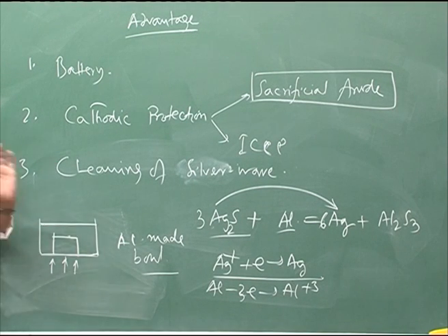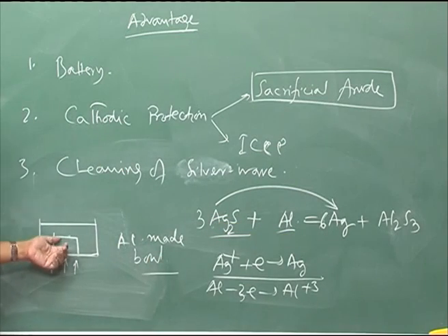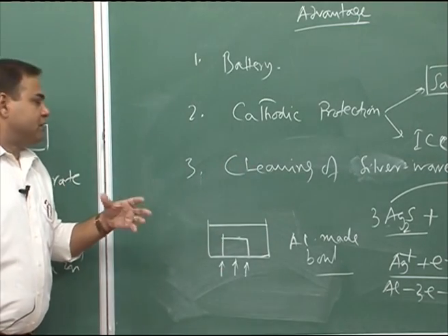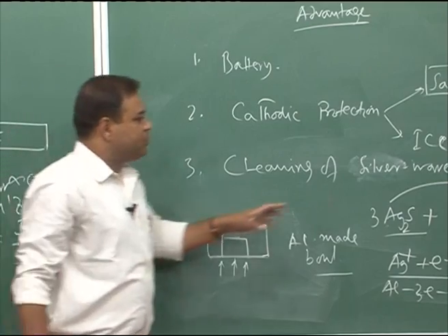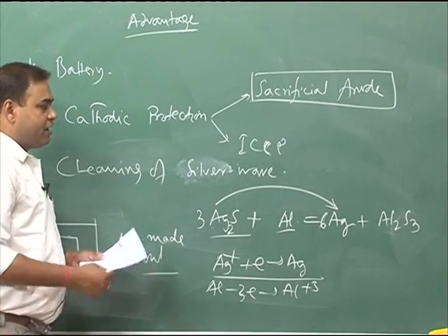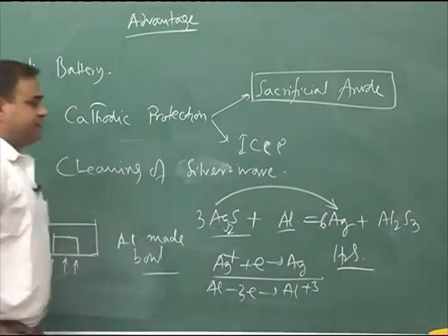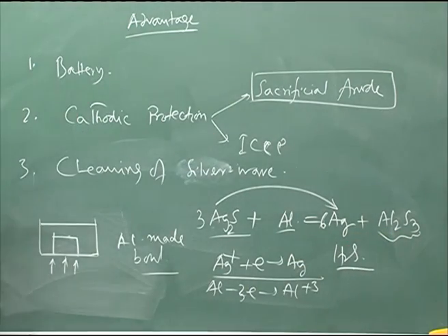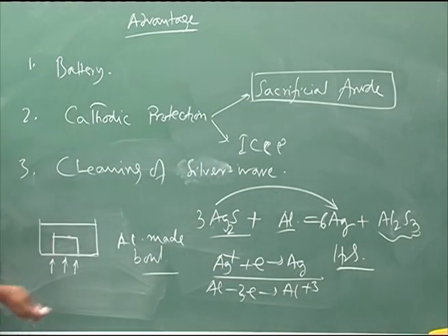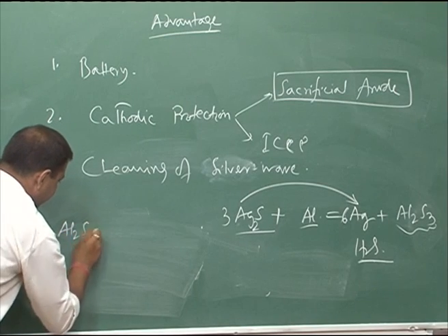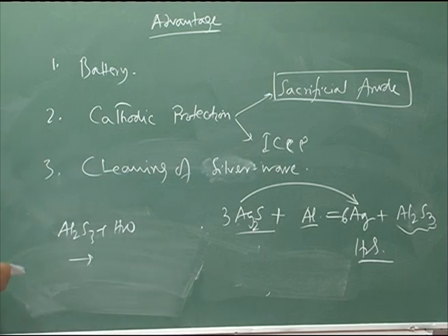Due to this there is no silver loss, silver again redeposits back, and during this process there is always a foul odor, just like a rotten egg, because the sulfide hydrolyzes and the hydrolysis product is H2S.